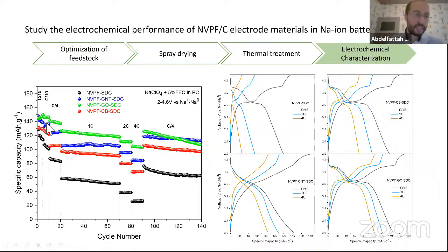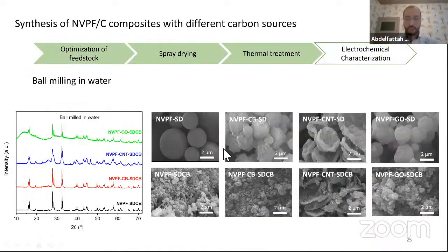This extra capacity, because the theoretical capacity is only 128 milliampere hour per gram, comes from the degradation of the electrolyte that we'll explain later on using the XPS technique. In order to increase, again, the electrochemical performances of all these 4 materials, we make the grinding using the same conditions as before, 30 minutes